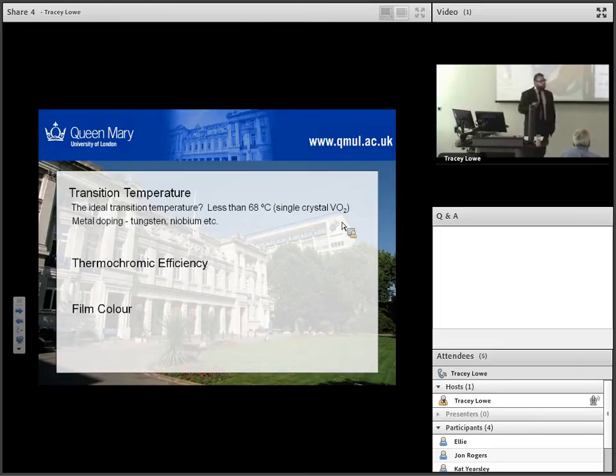There have been approaches done using metal doping. Tungsten, niobium are particularly good at this. A couple of atom percent incorporation of tungsten, for example, will drop that transition temperature down to somewhere around 22 degrees centigrade, where you might actually want it. There is a problem with that, which I'll explain in a moment.